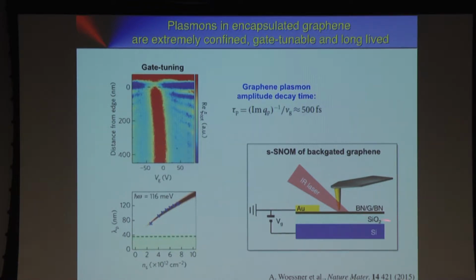And then we can change the Fermi energy or the doping in the graphene here. And so we did the following. We now scan to an edge here, and we see these fringes here. So that's the edge of the graphene, and we see the standing wave pattern in this direction. And in the horizontal axis here, we plot the voltage that we apply. So here we have a spatial coordinate, and here we have the voltage. And what we see is that these oscillations, the spacing from peak to peak, gets narrower and narrower. And that means if we reduce the voltage here, we shrink the wavelengths.